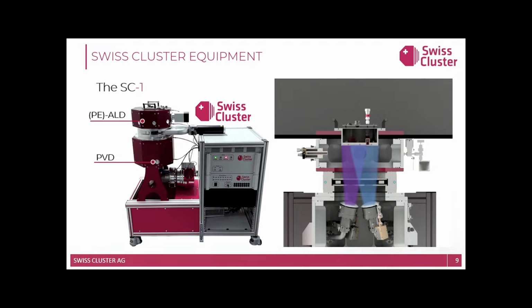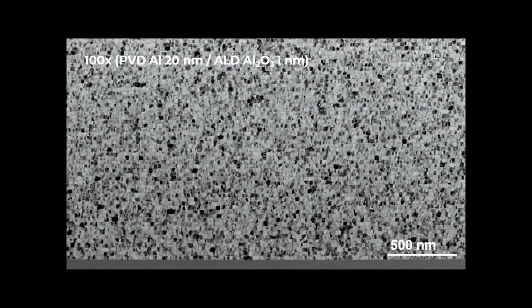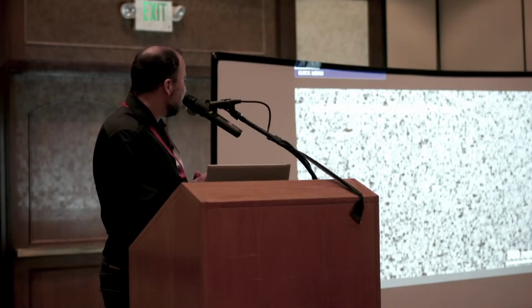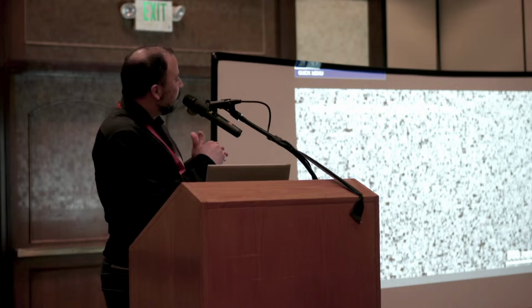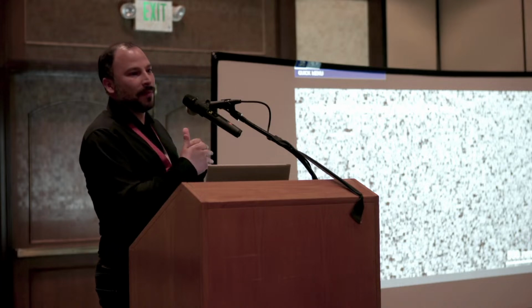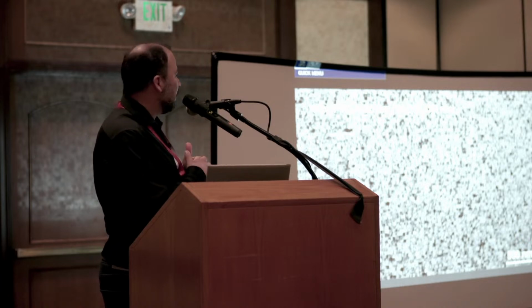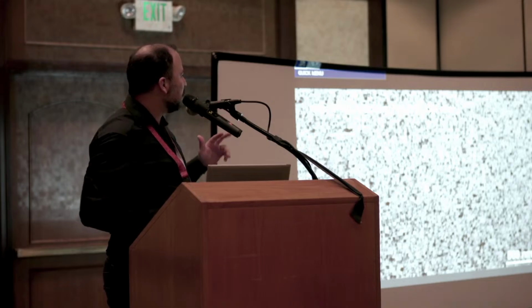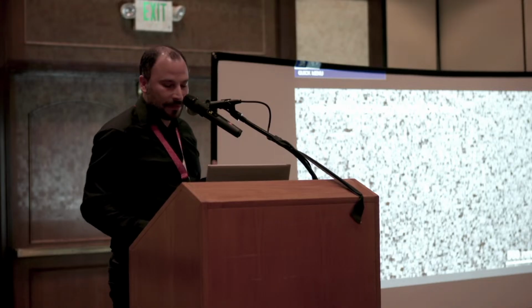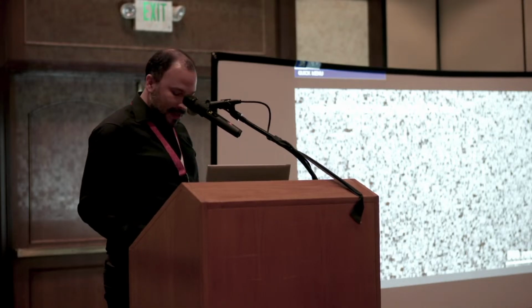So, of course, the first system that we created, when we created this first machine back in 2020, the first model material system that we wanted to create was aluminum and aluminum oxide. So we sputtered 20 nanometers of aluminum with magnetron sputtering, of course. And then every 20 nanometers, we deposit 1 nanometer of aluminum oxide by atomic layer deposition. And then we do this hundreds of times until we have a 2-micron thick film.